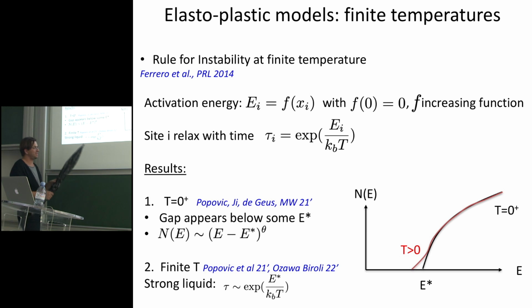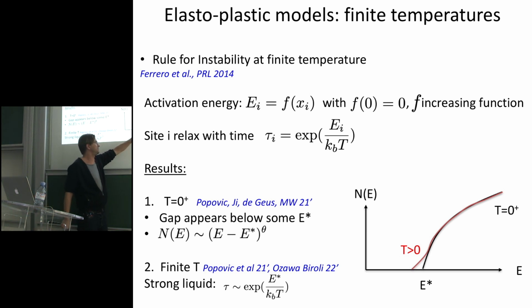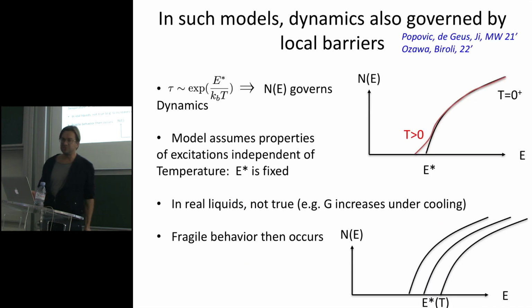If you are at finite temperature, actually you have a small change. Instead of having a sharp gap, you have an exponential tail, but it's a small quantity, just on the scale of the temperature T. And what you find also is that the dynamics in this model is just activated, and here enters the gap energy E star. The key point I want to make is that in those models, despite the fact that you have interactions between local excitations, it's still true that the dynamics is governed by local barriers, right? If you can measure N of E, you can measure E star, and you can deduce the dynamics from it.